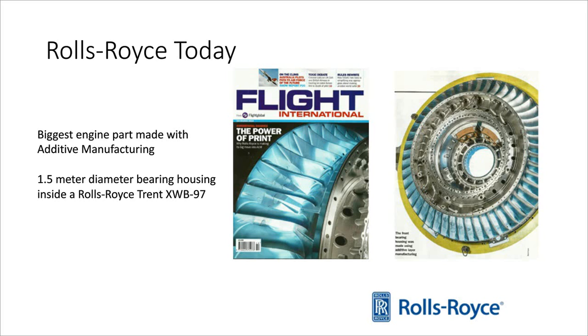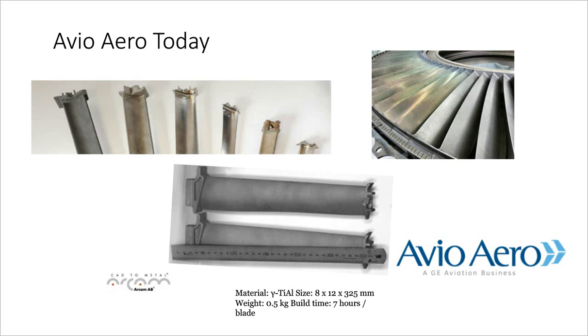So that's also very impressive. If you go into more production in aerospace, GE Avio today is testing and plans to go into production by 2017 using turbine blades. As you can see, these are made out of titanium aluminide, and you can actually build these pretty fast with EBM technology. You can build a blade in around 7 hours. They're doing testing and currently flying these. And like I said before, they'll try to go into production by 2017.